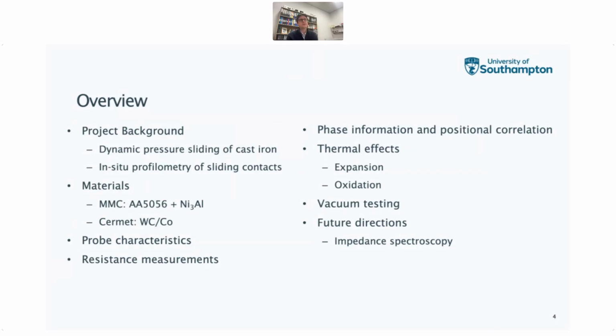So we're going to look at a metal matrix composite, and this is an aluminium alloy, a work hardening 5000 series aluminium alloy with a distinct second phase of a nickel aluminide as an intermetallic phase. And then we'll also look at a cermet as well, a hard-facing engineering cermet, tungsten carbide, cobalt. We will look at when you try and do electrical contact resistance measurements in a nano-indenter, some of the characteristics of the tip that you need to consider when you do these measurements.